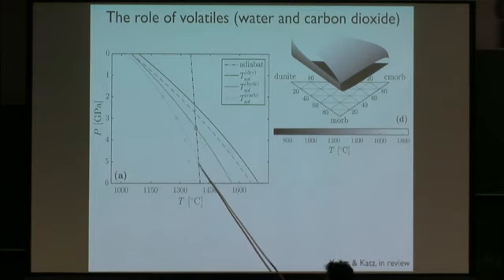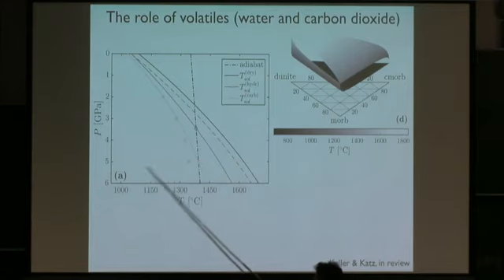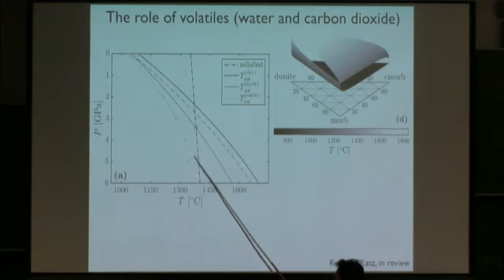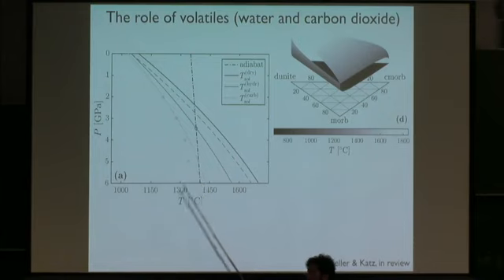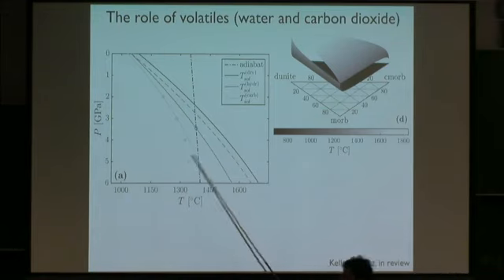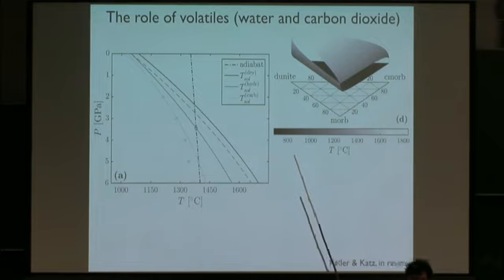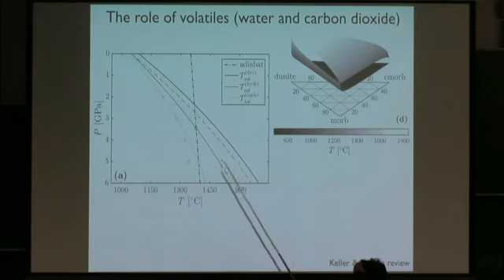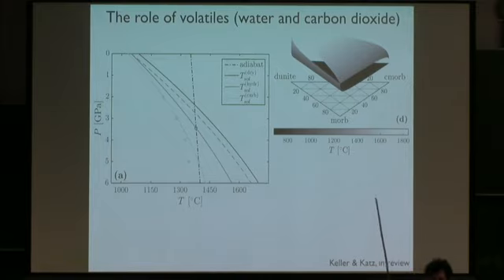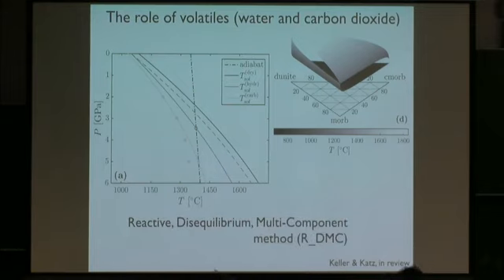So you see that you cross the carbonated solidus at about 5 GPa. Now these are data from Rajdeep Dasgupta. If you allowed your solidus curve to follow this, then you'd be crossing the solidus at such great depths that your model would basically need to be a global mantle convection model. We don't want to do that. Plus, there's some question about the oxidation state, which controls where you actually would cross the solidus. But in any case, the general systematics are that volatiles will lower the solidus temperature or increase the pressure at which you cross the solidus. And so we put this into the framework of a reactive disequilibrium and multi-component model.